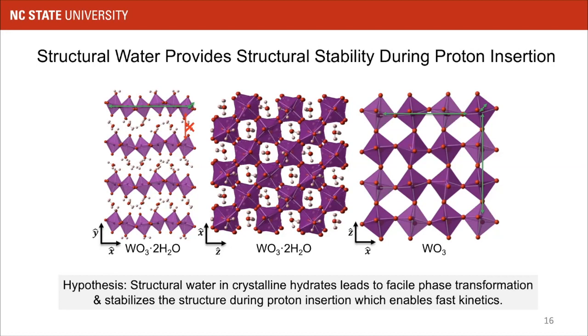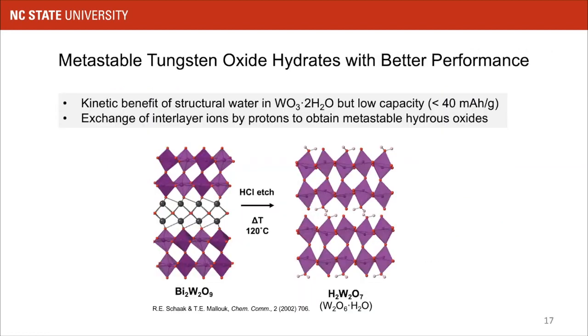So it's essentially like a glue keeping these layers together and not rearranging so much, as in the case of the anhydrous tungsten oxide, where you have more of a floppy crystal structure, if you will, where there's no reinforcement coming from the structural water network. So this was our revised hypothesis for what's happening with protons in a crystalline hydrate material. With this work, we showed the kinetic benefit of structural water, but the capacity is very low. We're not only using tungsten here, but we also have a lot of structural water molecules, so that all decreases the specific capacity. So we were on the hunt for tungsten oxide hydrates that could have better performance.